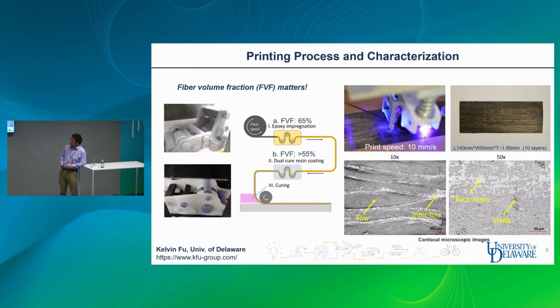Okay. So like I mentioned, the concept is very simple because epoxy cannot be cured during the printing, so we don't need to cure the epoxy. We just provide a soft layer on the outer surface. And when the material is exposed to the UV light, the outer surface could form some hard shell. We call this cladding technology. So this hard shell could help form this IPN, interpenetrating polymer network. And then the 3D structure can be formed, and then you can do any post-treatment in the oven.